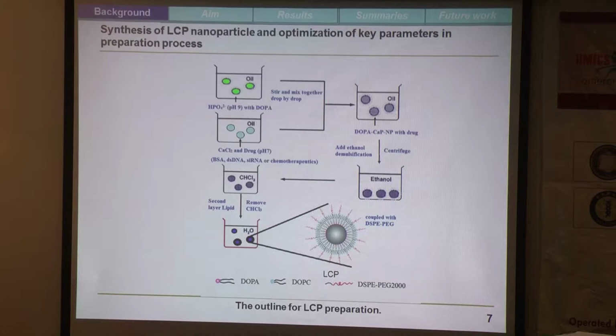In our study, the LCP nanoparticles were prepared using a modified two-step method. In the first step, briefly, during the synthesis of the particle, the amphiphilic and anionic lipid DOPA was added into the microemulsion to form the calcium phosphate cores with the first layer lipid coating. And after that, the second lipid layer can be easily coated outside the first layer by a film rehydration method.